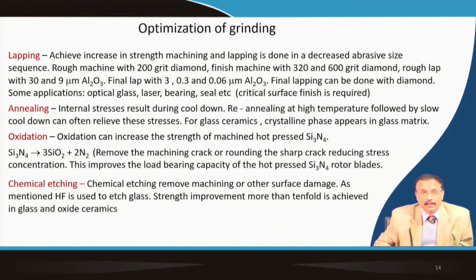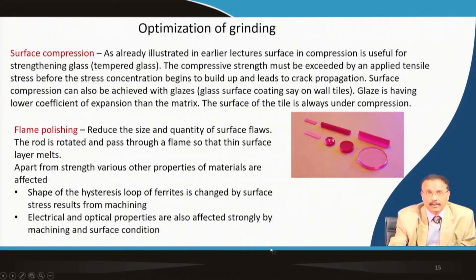Chemical etching is done to remove the machining or surface damage. HF is the chemical that is used for glass. In this kind of glass, the strength improvement is almost tenfold as compared to the normal glass, or for certain oxides also this chemical etching is found to be quite good.